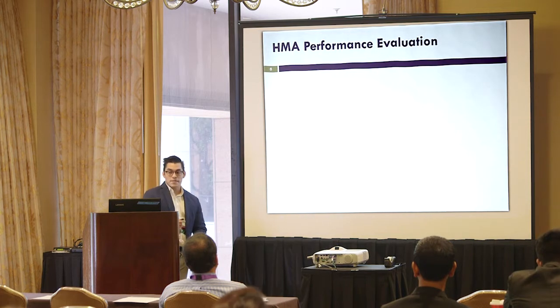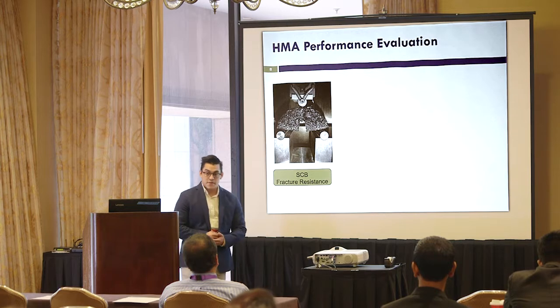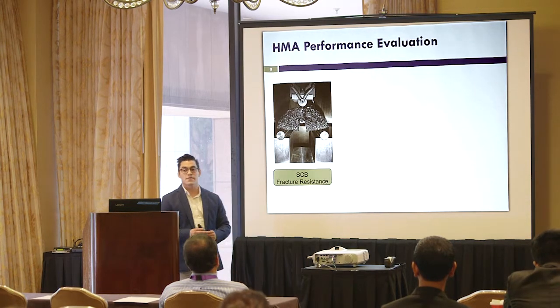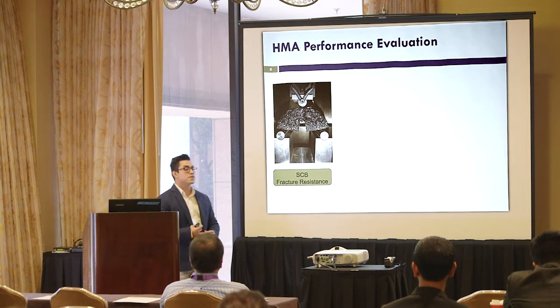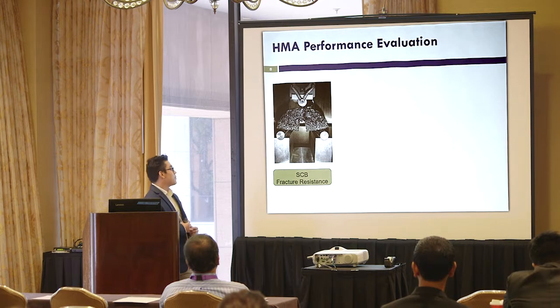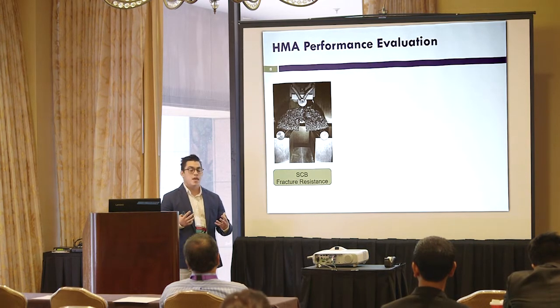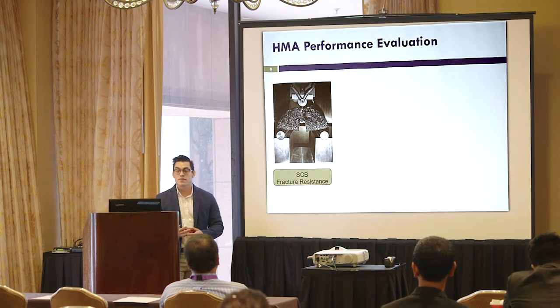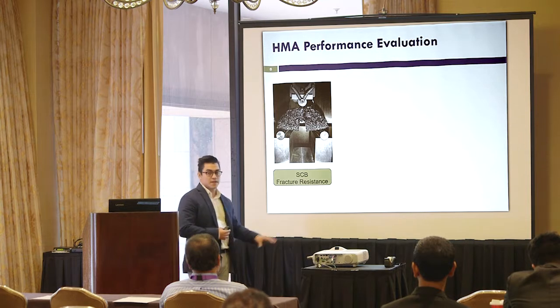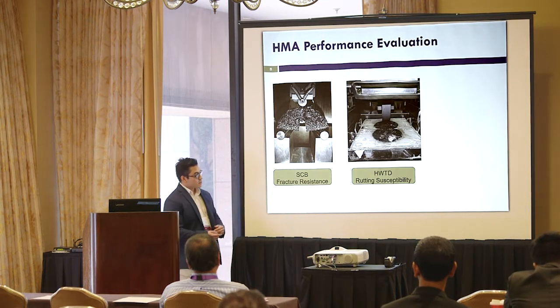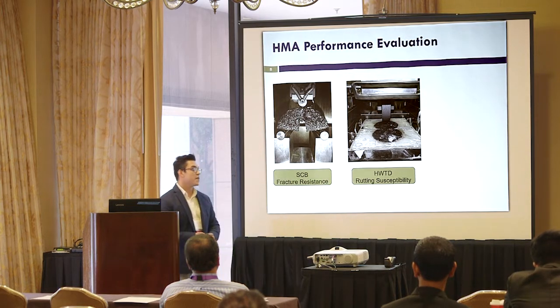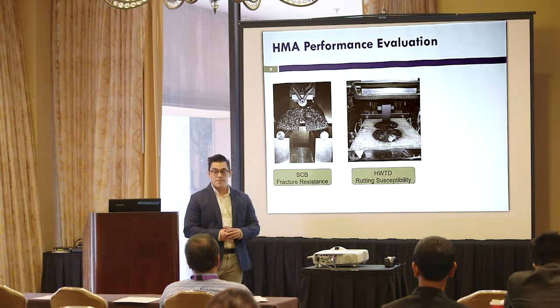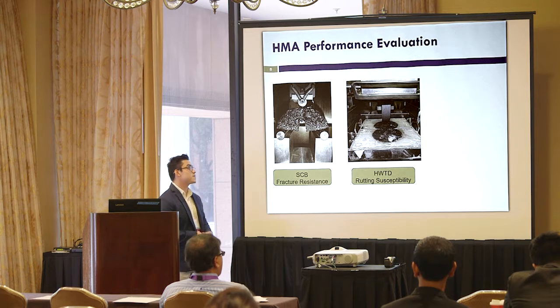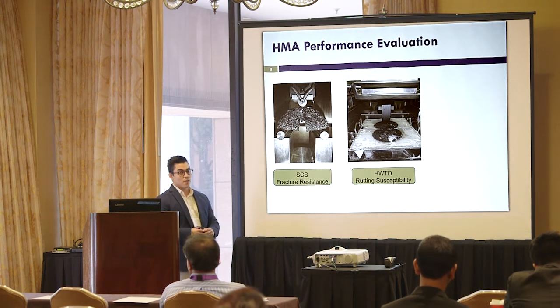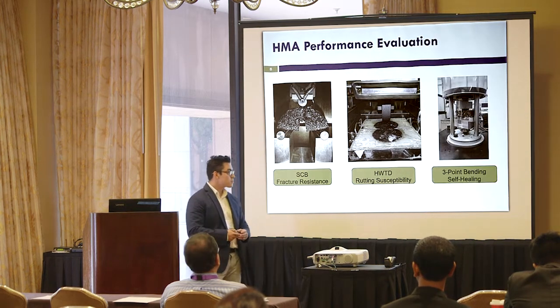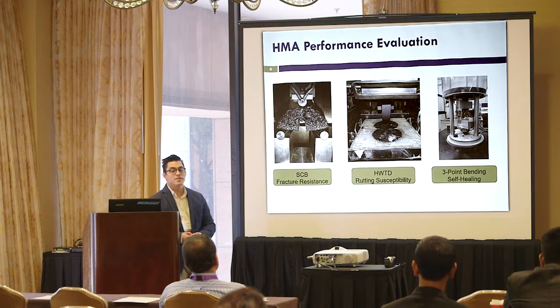For HMA performance evaluation, we use a semicircular bending test to measure the fracture resistance of the different mixtures. So basically we use a strain control test, 0.5 millimeters per minute at 25 degrees Celsius. And we are getting the Jc value, or critical strain energy release rate, from these tests to evaluate the fracture resistance. For the rutting susceptibility, we performed the Hamburg wheel tracking device test. We submerged the specimens in water at 50 degrees Celsius, and the test was stopped after 20,000 passes of the steel wheel. And lastly, we have the three-point bending test setup that we use for the self-healing test.